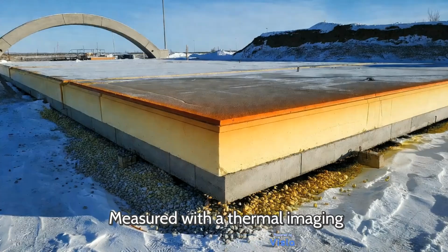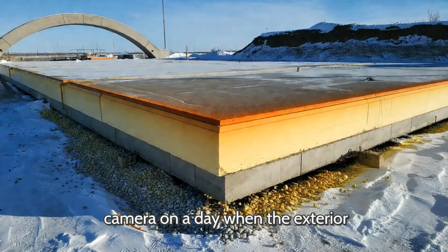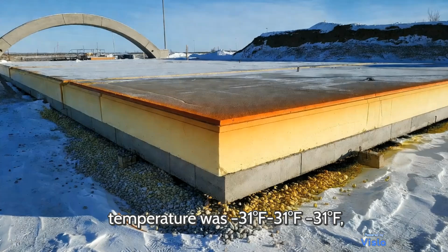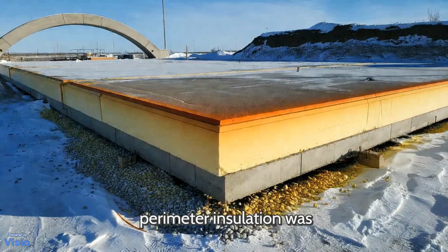Measured with a thermal imaging camera on a day when the exterior temperature was minus 31 degrees Fahrenheit, the surface temperature of the slab edge at a point where the perimeter insulation was installed was 24 degrees F.